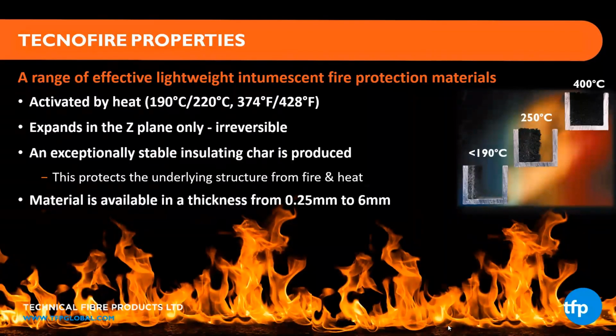It's going to expand directly at the heat source, not just necessarily flame, but it's Z-plane only. So it's going to directly react to the flame or the heat that's coming after it. It is irreversible. Once we expand, it doesn't shrink back. The hope is to have a very exceptionally stable char. That's what you need to survive the fire event. As you have air blowing, vibrations, different components of a fire, that char layer staying intact is very crucial. So we do have a product that does end up with a very stable char layer to keep your structure protected. We offer this in different thicknesses.